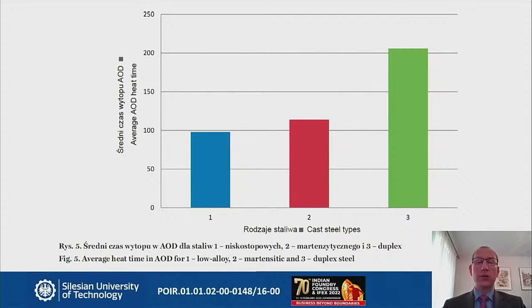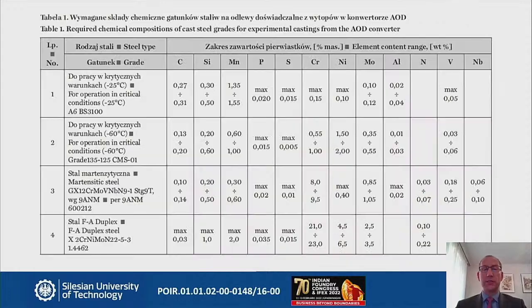And as I said, we targeted several grades of steels. So here you can see the picture with the average heat time for low alloy, martensitic, and duplex steels. And here you have only several examples of the chemical analysis of the steels we were producing to show you how complex the project was, how different the grades were, and how many alloying additions were added to the steels for the particular grades.